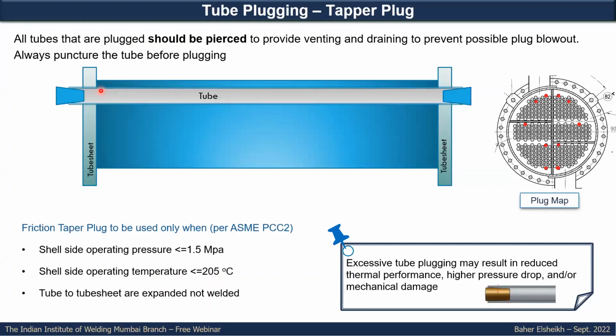During the application of the plug, it is recommended to pierce the tube before. Here we are talking about plugging tubes with thickness loss, but not leaking. If it's leaking, no issue. But if it's not leaking, you need to pierce the tube, because if you apply the plug like that, some media will be trapped in the tube, and during service and heating, it will create some vapor pressure. Increasing the pressure might cause the plug to fly out, and it might cause an incident. So it's highly recommended to pierce the tube as per PCC-2. Two holes need to be applied before applying the plug.